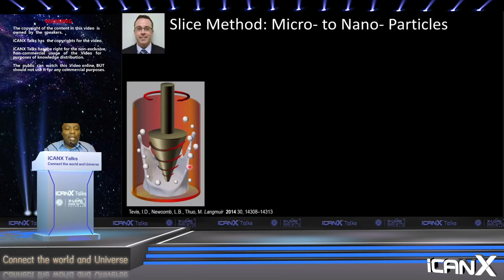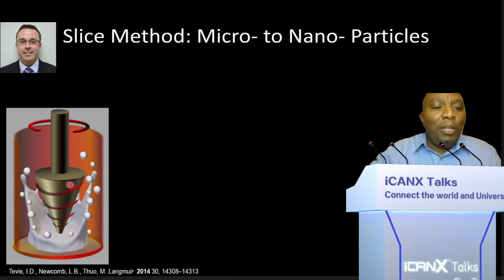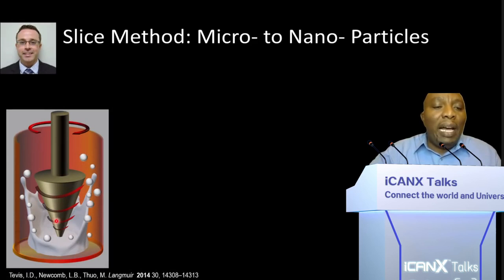How do we make those particles? It's very straightforward. As a former mentee of George Whitesides, you can imagine I'm making things as simple as I can. So here we use a method we call SLICE, and SLICE is basically shearing liquid into complex particles. And as we shear these particles, we also are doing chemistry on their surface to allow the distribution of those components and the oxide to be very smooth, and also drop them into a size that will allow them to significantly undercool.